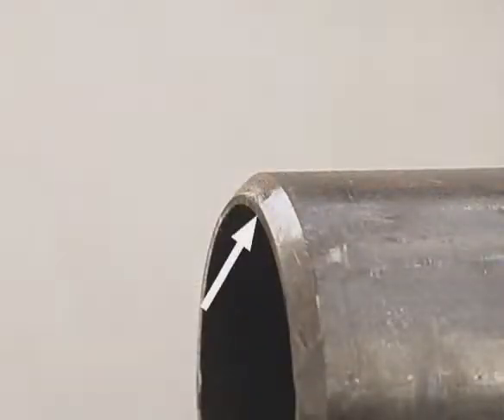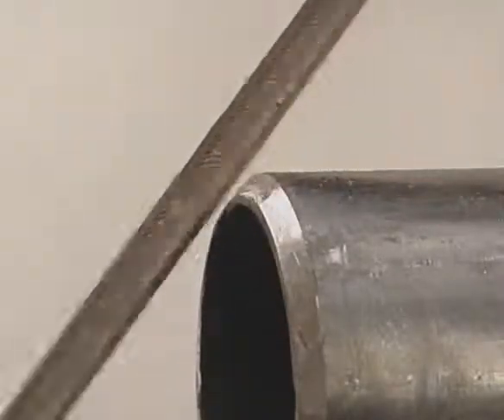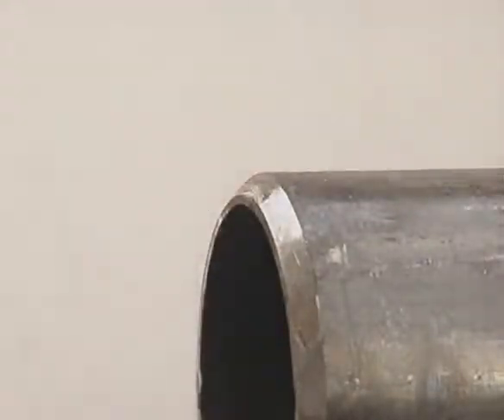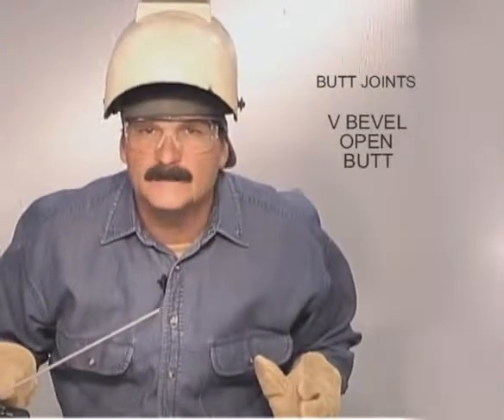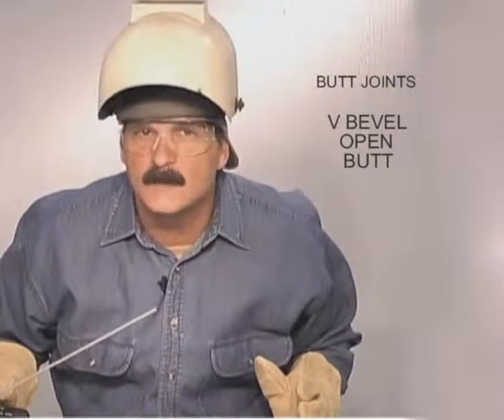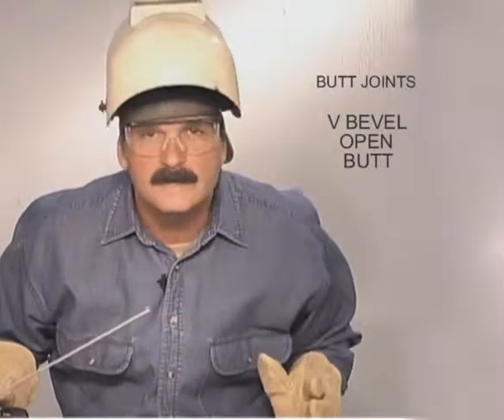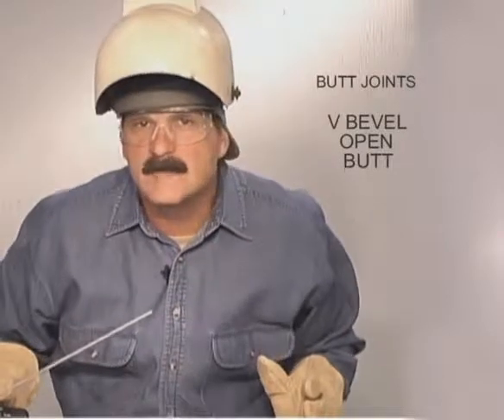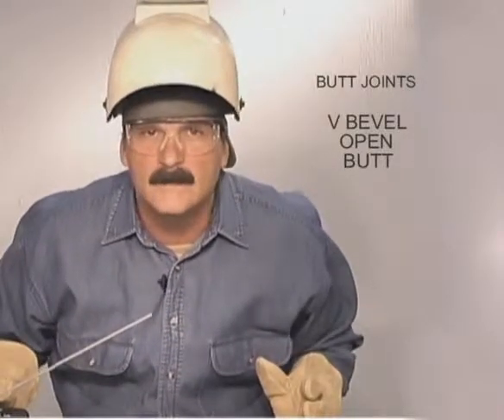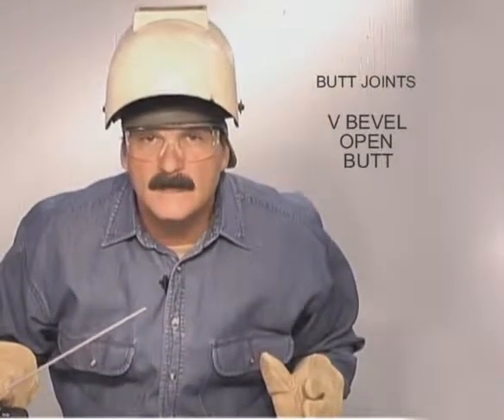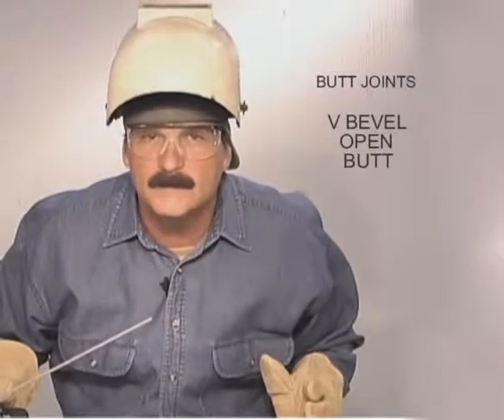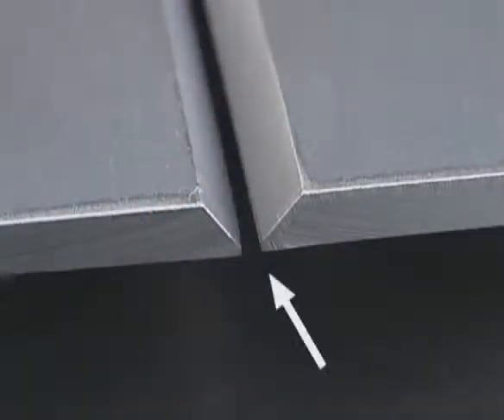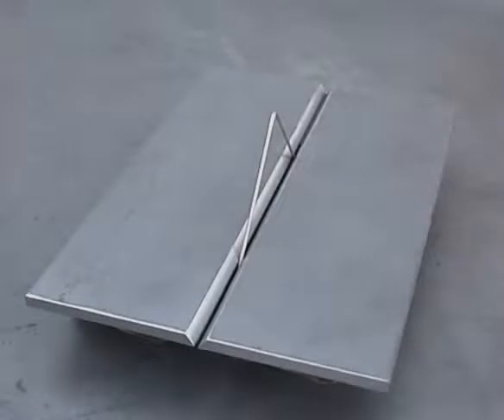The landing should be uniform. Use a file to knock down any high spots. With a 1/8 6010, I use a 1/16 oxyacetylene welding rod as a spacer with around a 16th landing. The size of the gap and landing can vary a little, but when you figure out what you like, try to keep it consistent for every weld you make. Line up the bottom edges of the metal. With a spacer to adjust the gap, run 1 tack, pushing the rod right down into the gap.